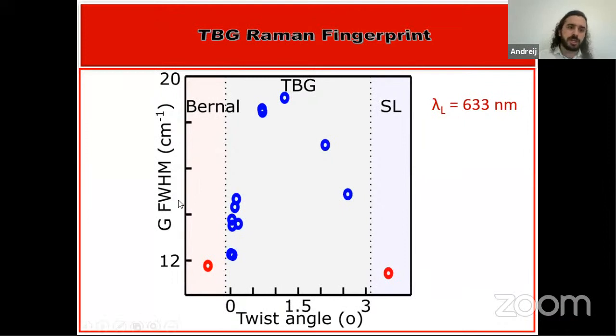So here we plot the G width as a function of the twist angle in blue, and in red we plot the Bernal and single layer for reference. For decreasing angle, we see that the G width increases, reaching a maximum, and below that, the G width decreases, reaching values close to the Bernal bilayer. So this is a Raman fingerprint. Everyone can use this diagram to calibrate the angle of your TBG. So you prepare the TBG, and once you know the angle, you can check it here.